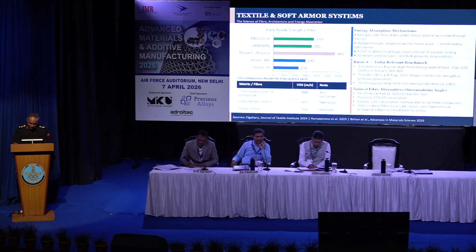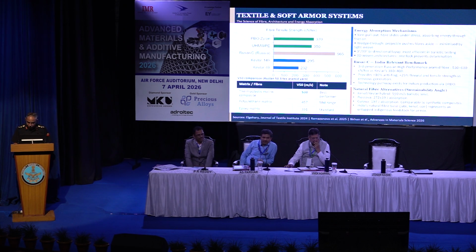The architecture matters as much as the fiber. A 90 and 0 degree bidirectional layup is consistently the most effective because fragments arrive from any direction. The fiber network must arrest motion in all directions simultaneously. The matrix material is a procurement decision, not a science decision. Same fibers, same weight. Thermoplastic matrix gives 538 meters per second V50, whereas epoxy gives 391, a 38% improvement by changing only the binder. That is the specification lever available today. So we have to be very aware that with the same material, if the specifications and structural changes are made, the outcome can be improved.